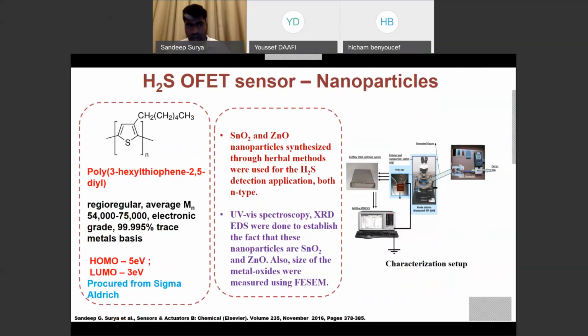In my case, I have used organic field effect transistors again, but here with a different approach compared to my previous ones. Earlier I tried the organic semiconductor alone, or I made composites. Here in this case, we have used P3HT as an organic semiconductor in combination with metal oxide nanoparticles. By the time we carried out this work, tin oxide and zinc oxide were heavily explored, but there were no low-cost processes available to synthesize these materials through green synthesis. So in this work, the receptor materials, the nanoparticles, were made for the very first time using a green synthesis method.